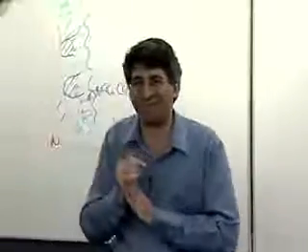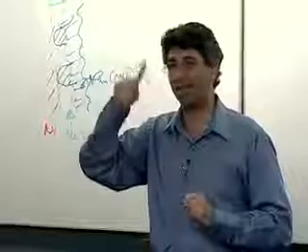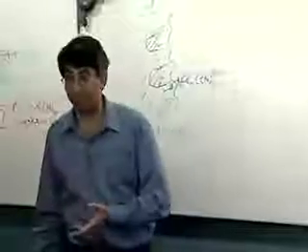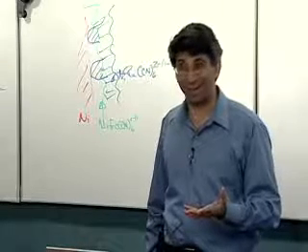The first thing we did was the brute force approach: we made up 50 of these electrodes. We made up an electrochemical cell with a volume of 1 milliliter, and we ran each electrode, cycling it with cyclic voltammetry for 30 minutes, for 50 electrodes in the same volume of solution. Then we looked for ruthenium in the solution by atomic absorption. We found about 0.1 parts per million of ruthenium after all of this, which is not enough to do that, and this is after running 50 electrodes. How could we ever see it with one? So that didn't sound too good.